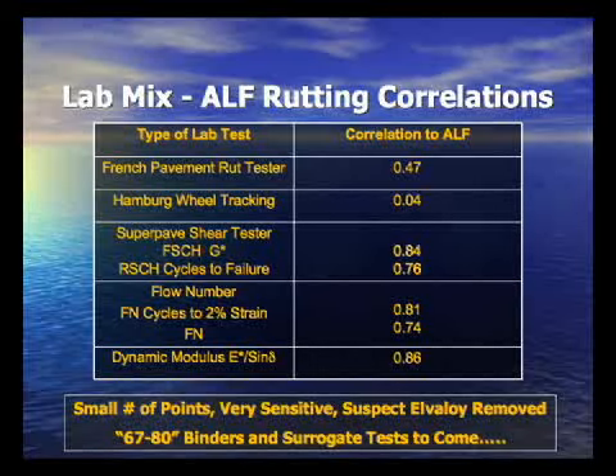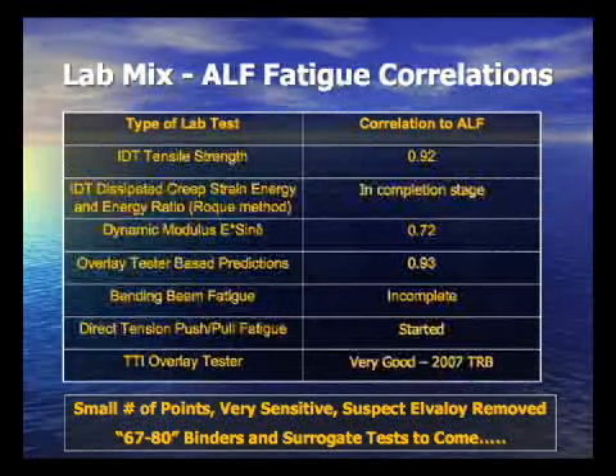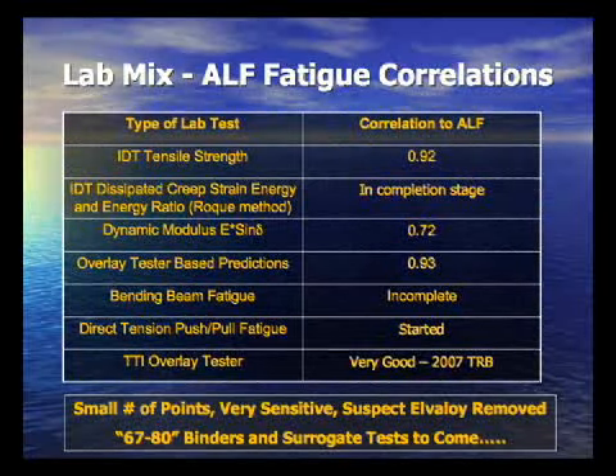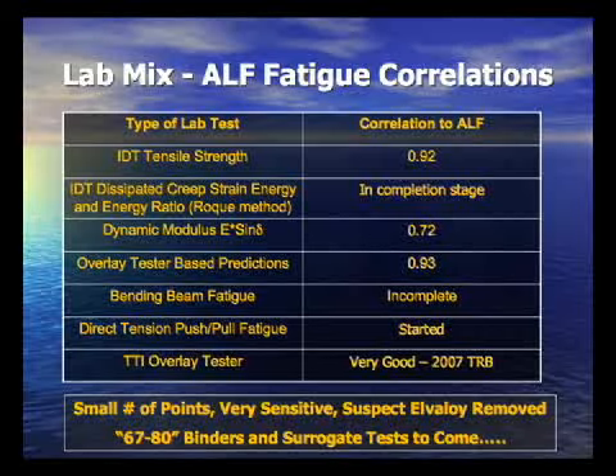So I'll get to some of the tests that have been completed. This is in terms of lab mix to ALF rutting. As I said, the French rut tester has about a mediocre correlation. This is R squared. The SST did pretty good, depending on whether you were looking at thin section, 4 inches versus 6 inch. The flow number also had a different correlation, but I want to bring in the science here and warn you about this. This is a small number of points, and it's very sensitive to the number of the points we're looking at, and also because this suspect mixture was removed. There were some issues with introducing the lime for anti-stripping into that, and I can get to that in the question section if we want to.